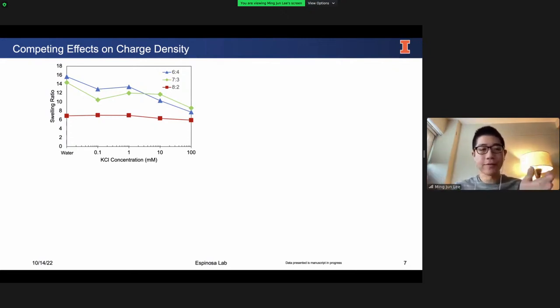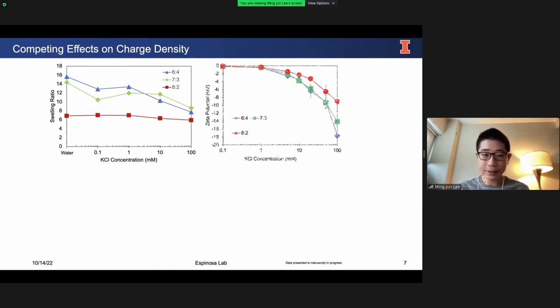And we see that for the hydrogels, I have 3 different recipes, the 6,4, 7,3, and 8,2. These are just the molar ratios of the copolymer. But in general, as the salt concentration increases, the swelling ratio of all these hydrogels is decreasing, it's getting smaller. At the same time, the zeta potential, a measure of the surface charge of my hydrogels, is also getting stronger and stronger. It's more negative as the salt concentration increases.